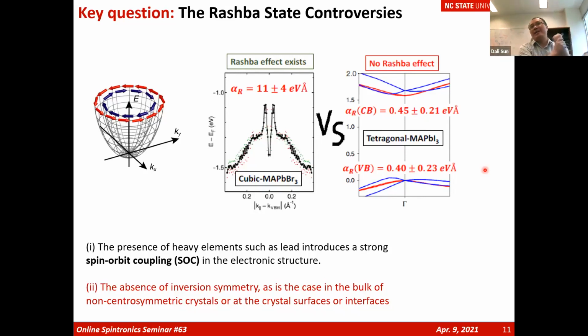So that's two forces starting to debate each other. One side says, yes, this is a Rashba state, we observe it by ARPES, no problem. But another group says, no, there's no Rashba state. Experimentally, we don't see second harmonic generation. In DFT, we don't see any spin splitting state. And even more questionable is the cubic structure of MAPbBr3. What's a cubic structure? Cubic structure maintains the inversion symmetry. There's no absence of the symmetry. How would you be able to observe Rashba effect in a cubic structure? It's really questionable for this field.